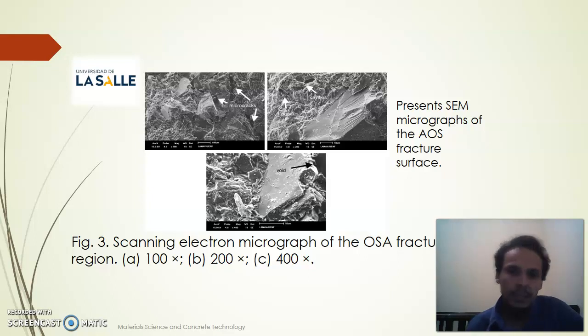Figure 3 presents an SEM micrograph of the fracture surface of the AOS. In this micrograph image, one should observe a good adhesion between the epoxy matrix and the residue particles. Figure 3: scanning electron micrograph of the fracture region of the AOS.